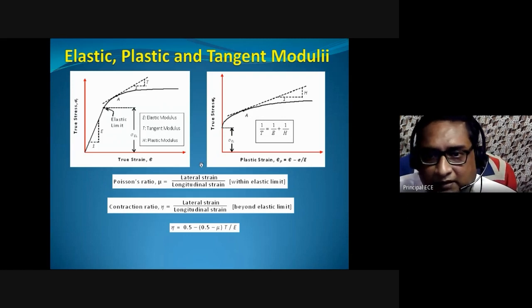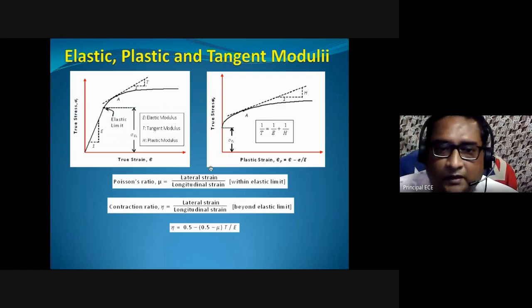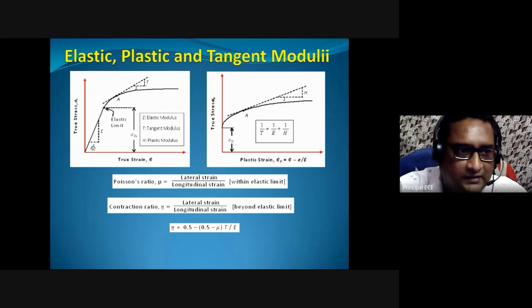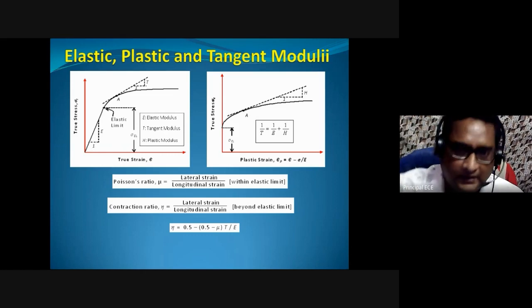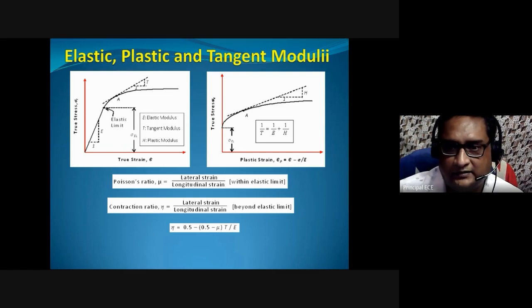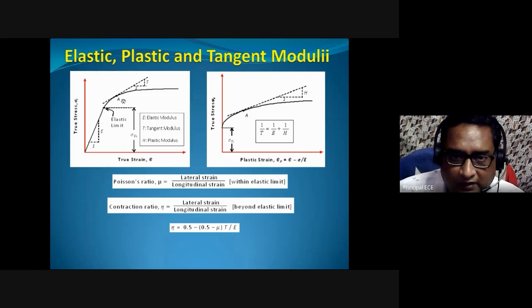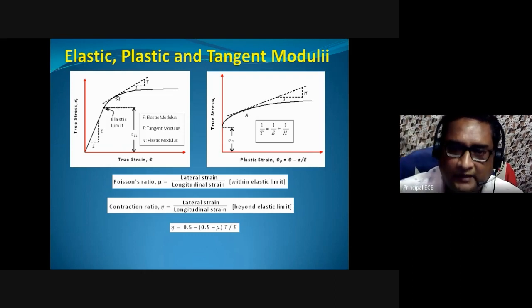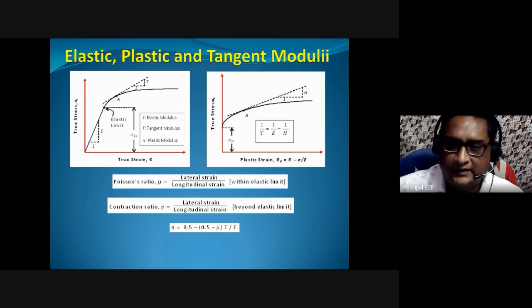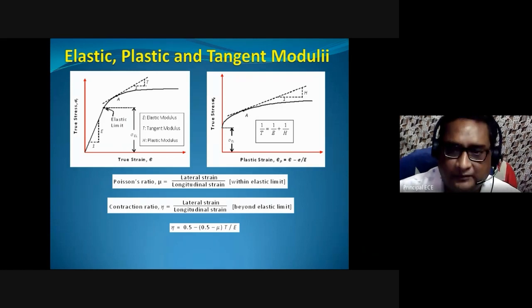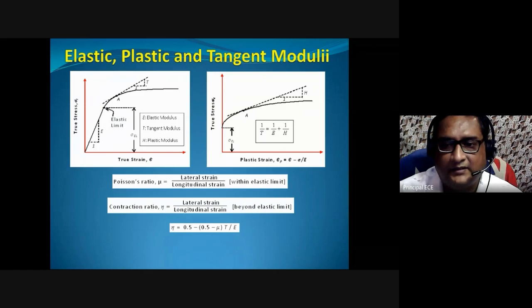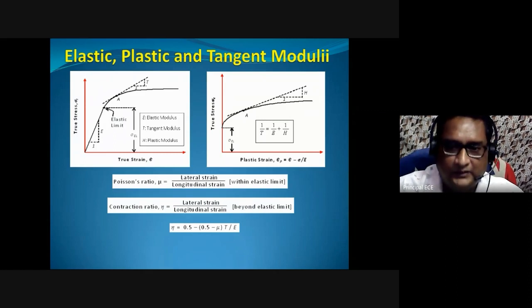In the second portion, it is the true stress versus the plastic strain. What is the plastic strain? If you take a point in the elastic zone, the strain developed is completely elastic. That means whenever we withdraw the loading, it regains its original configuration and the strain is zero. But at a point A in the plastic, nonlinear zone, if you withdraw the external loading, it does not regain its initial configuration. Some residual strain, some residual elongation, is left in the specimen. So the strain is composed of an elastic component and a plastic component. The plastic component is the total strain minus the elastic component.